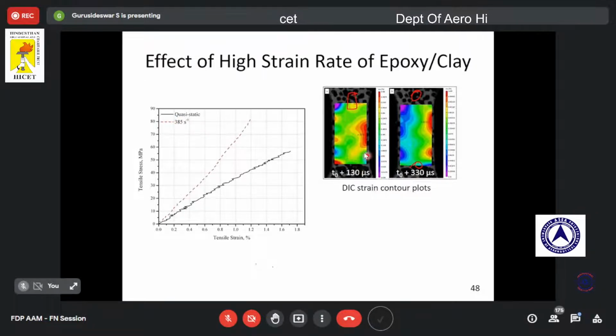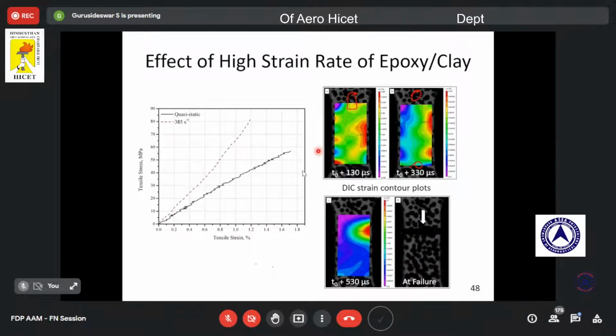This is the strain rate we achieved by using the drop mass setup, 385 per second. You can see the strain contour at different time steps. At the beginning there is a strain localization, again there is an increase in strain, and then a drastic increase in strain localization around 530 microseconds, and then the sample leads to failure. From this DIC technique we got the strain data, and from the load sensor we got the stress data. With this idea, we were able to get the tensile stress strain curve for epoxy samples at high strain rates.